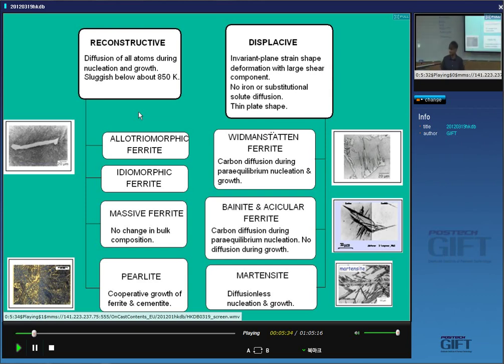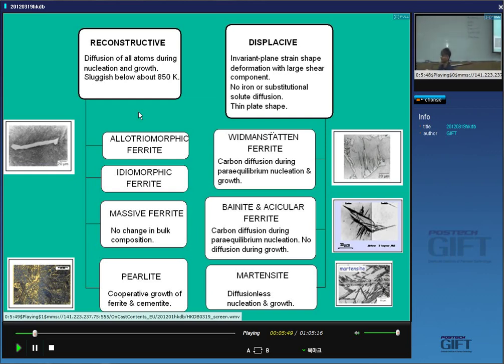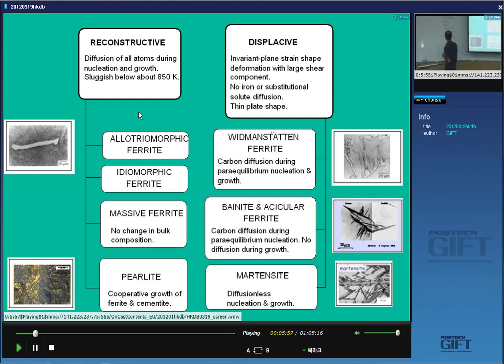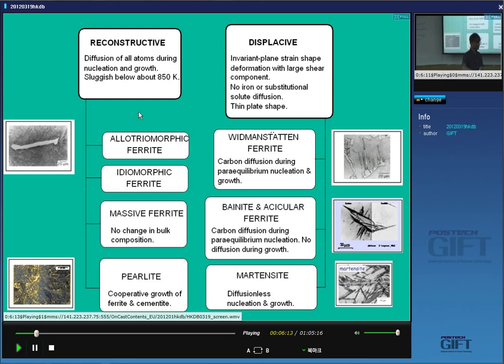What about transformation temperature? Very low. Athermal. So what does athermal mean? It depends on the temperature. So it's an athermal transformation — in order to get martensite, I have to cool to a certain temperature and I'll get a certain fraction of transformation. To get more transformation, I need to cool further. If I hold it at a particular temperature for a long time, you will not get more martensite.